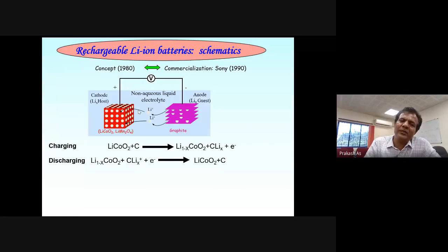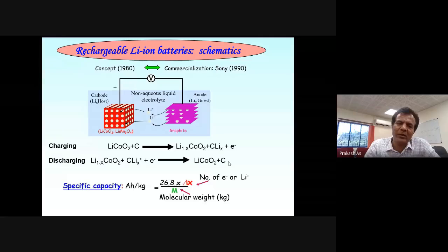When you charge these batteries, lithium is removed from the cathode, the electrolyte transports it, and it is intercalated into the graphite. So this material is getting oxidized and this material is getting reduced. The electrons move around through the external circuit. When you charge it, from lithium cobalt oxide plus carbon, you deintercalate lithium and intercalate it into the carbon, and the equivalent number of electrons is released from this reaction. When you discharge it, the opposite happens, and you form back lithium cobalt oxide and carbon. So this is how it happens.